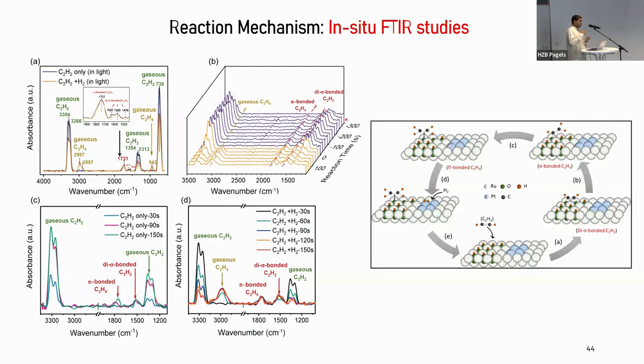What we realized, when we removed the coating agent on these clusters, some of the Ru oxidizes into RuO2, RuOx, right? The acetylene activation is done onto the RuO2 site, and not the RuPt. RuPt is only helping to split the hydrogen that is required to add into the acetylene. But the real catalysis was happening onto the RuO2 site. And now, when you do the reaction, because you have the hydrogen and because you have plasmonic, H2 dissociates and converts all that RuO2 back to RuPt.